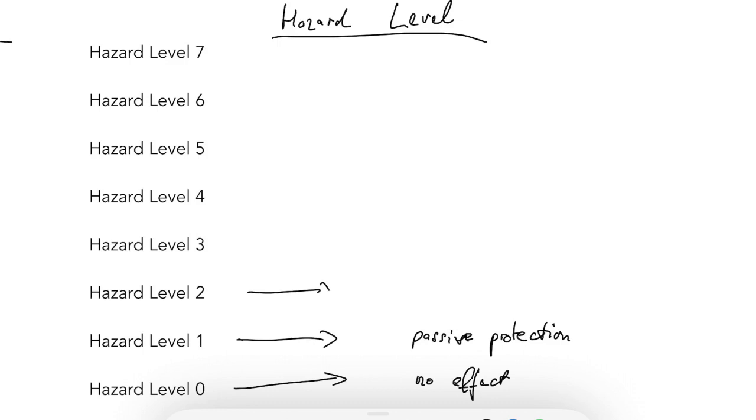Then let's go to hazard level 2, which is defect. Defect means something inside chemically has gone bad. Typically, if you start the thermal runaway and you have a slight decomposition of the solid electrolyte interface, for example, you have a defect and you cannot easily just switch it off and then everything is okay again.